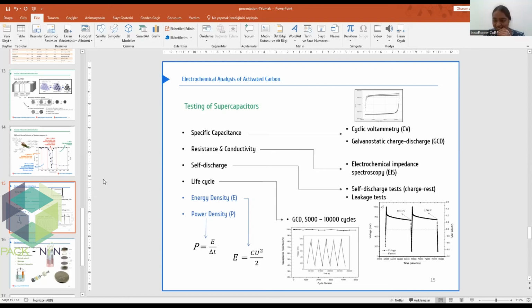And again from Sajal, how can we optimize the amount of binder and what things need to be considered? You can optimize the binder by changing the binder amount in the electrode slurry. In most cases, we use 80% electrode active material, 10% binder, and 10% conductive material. In my work, I use carbon black as conductive material and PVDF for binder. You can decrease or increase the binder in several experiments and look at the results to find the optimum binder. The optimum binder amount depends on the electrode active material, so you should do some experiments.